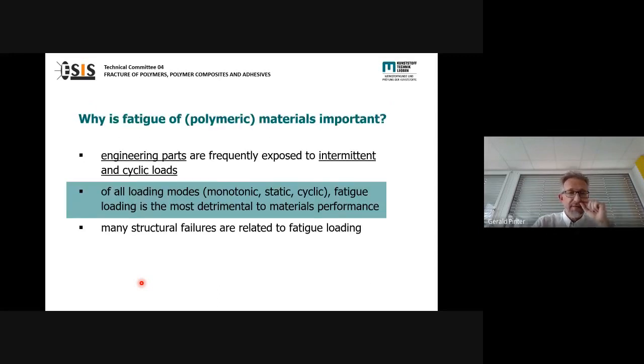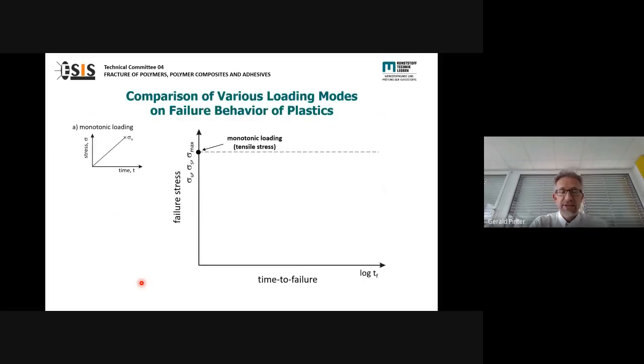So why is fatigue so important and so critical to consider? That can be easily explained by the following diagram. If we have a conventional monotonic load, so we take a specimen or a component loaded under a defined deformation rate, typically we find then a maximum stress. You can see here in the diagram failure stress over time to failure. If we apply now a long-term static loading, a kind of creep loading, what we typically find in polymers and viscoelastic materials is that this failure stress is decreasing over time because of viscoelasticity in the polymer.